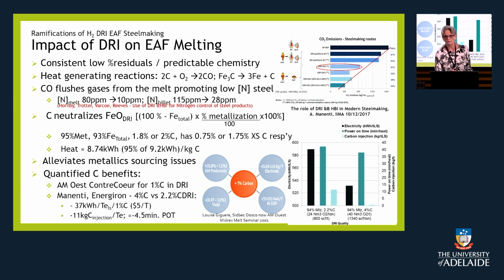And that will add to the chemical reactions in the system. The DRI also alleviates issues of sourcing irons. In countries such as Argentina, it's very difficult to get any scrap, certainly not any good scrap, for example. There's some quantified benefits at the bottom there from ArcelorMittal in Contrecoeur. They said 1% carbon was basically going to improve your yield, meltdown kilowatt hours by 25%, and it was going to reduce the electrodes wear. The Energiron chart on the right-hand side actually shows a comparison between 4% carbon and 2% carbon, and they actually found the 37 kilowatts per ton reduction using 1% carbon, 11 kilograms of carbon reduction, and also 4.5 minutes off power on time.